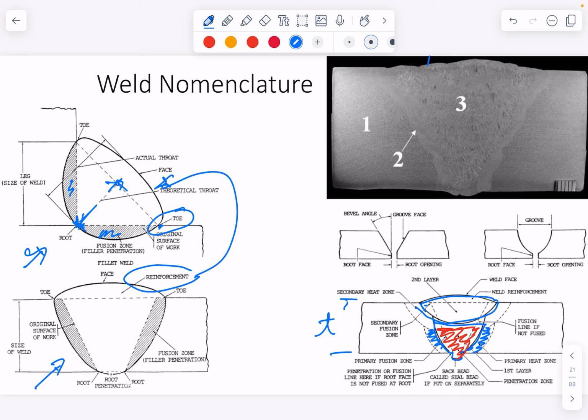And of course, whilst you're doing that, you can see here in this image, you've got a heat affected zone through here. You've got a fairly fine microstructure in the as rolled plates. And in the weld, you can see we've got some fairly large crystals or grains. So that's cooled relatively slowly. So it's fairly obvious that through here, there is going to be a variation of mechanical properties. So you just got to be mindful of that.